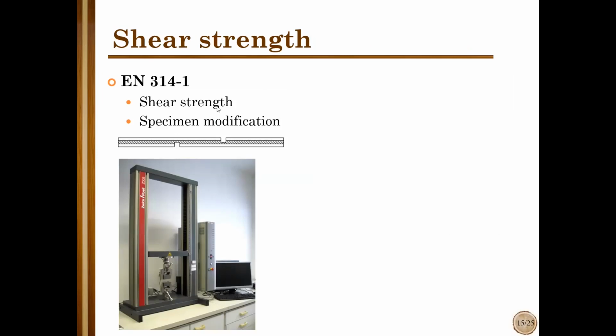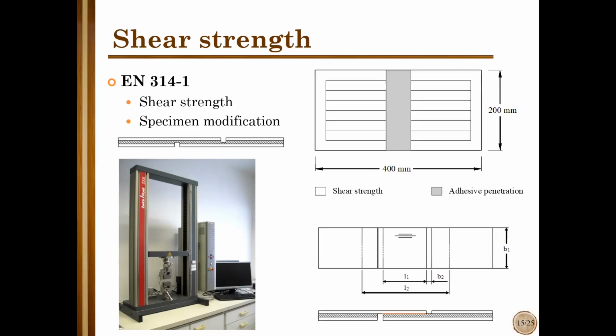We used the standard for plywood with some modifications. Here you see a specimen for the plywood shear strength test, but since we were focused on the correlation between adhesive penetration and shear strength, we made slightly different specimens. You can see it here below. It was cut to the adhesive bond line, and this was the bond line which was also investigated in terms of adhesive penetration. So we could focus on the same bond line which was analyzed by microscopy, and the shear strength test was also focused on this bond line.